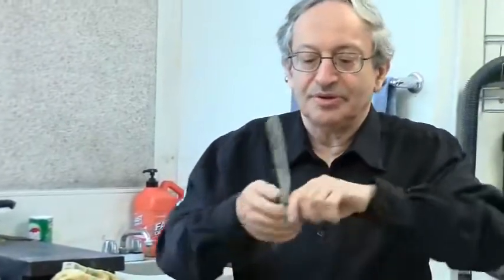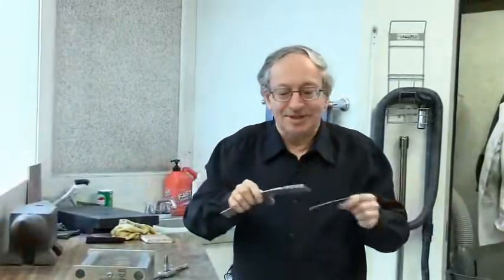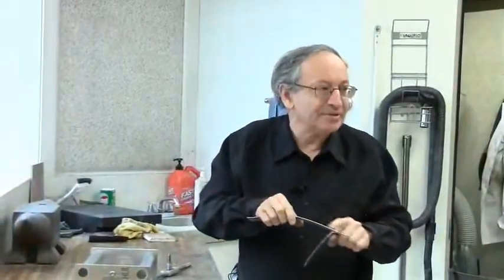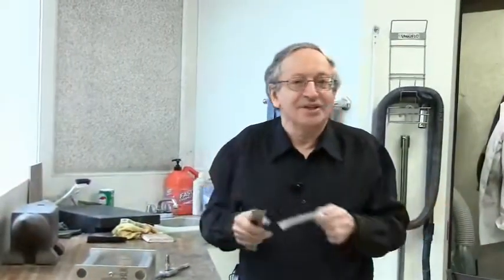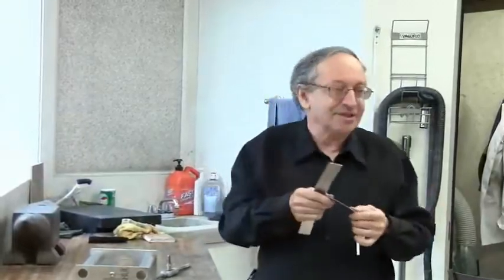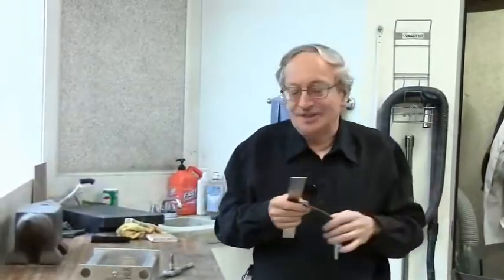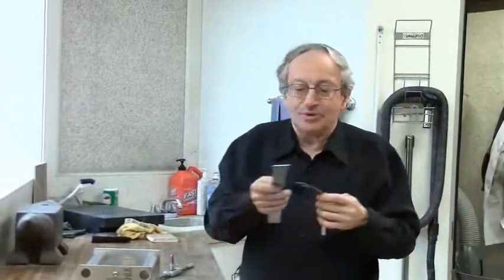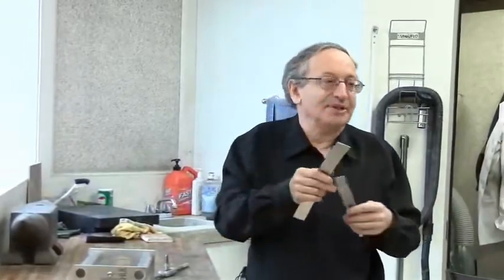So this was sandblasted, properly done, properly cured by all the rules. And if I do it in peel mode, it has 0 strength, which is surprising. The epoxy was spread and everything was good, it has 0 strength. And if you try it with any other adhesive, you get the same results. So never design something in peel mode. Sometimes you don't think you're designing in peel mode, but it's actually in peel mode.